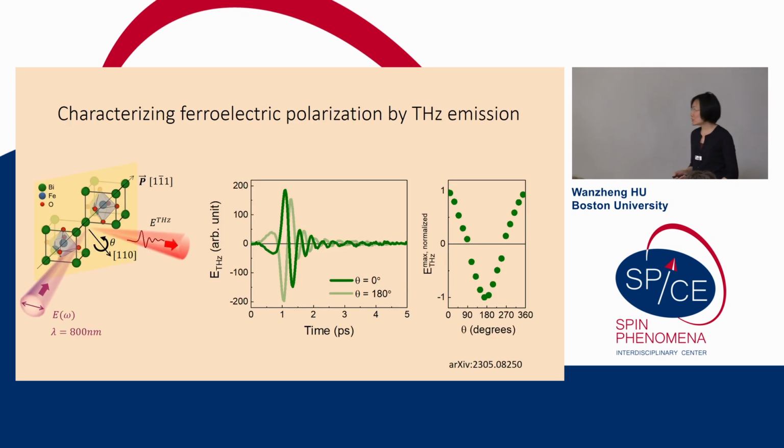First, I'm going to show you this terahertz emission experiment. This is an equilibrium measurement. There's no mid-IR pumping. In this experiment, we rotate the crystal orientation around the surface normal, and we shine in a linearly polarized 800 nanometer beam, and it will generate terahertz emission. Then we measure the terahertz field along a fixed polarization direction.